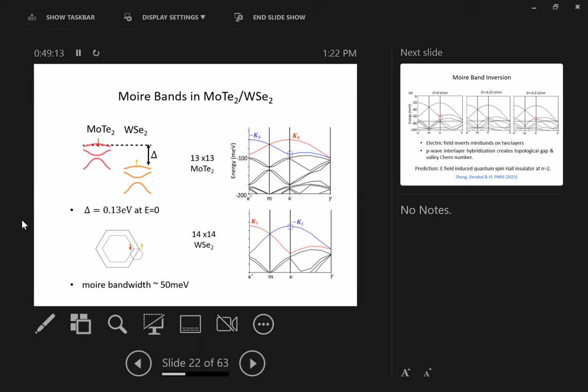So again, this is the band structure on the MoTe2 layer and on the WSe2 layer. In both cases, you see that because of lattice corrugation, Moiré bands are formed. There are these mini bands separated by small gaps. And this can actually be fitted very well by a parabolic band in the periodic potential. The two different colors correspond to electrons of different spins. So all you need to focus on is electrons of one spin, let's say the blue bands.